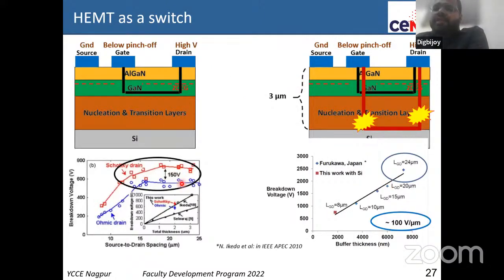So what people have shown, this is not from our group, this is literature from Japan. If you increase the spacing between gate and drain, you can keep increasing the voltage that you're blocking until the field will penetrate and reach silicon. Once it reaches silicon, silicon will break down. That's why after a certain spacing, the voltage does not increase. The y-axis is breakdown voltage, the x-axis is the spacing between the gate and drain. You can see that after a certain point, the voltage does not increase. That's because vertically it has broken down, because silicon is the weak link.